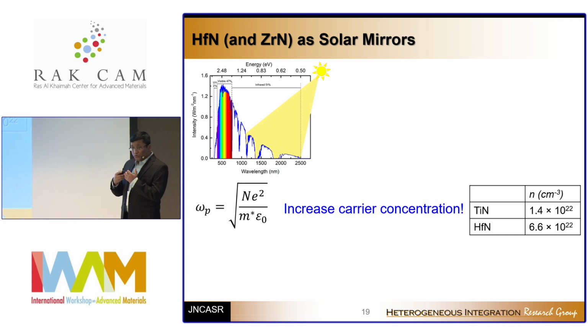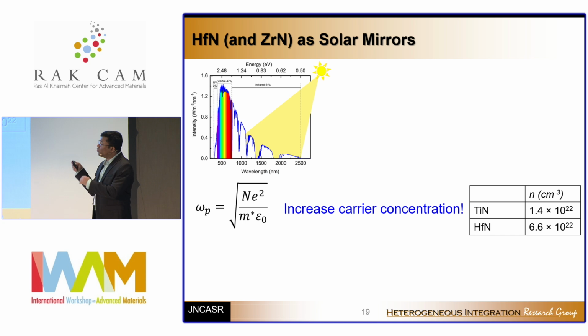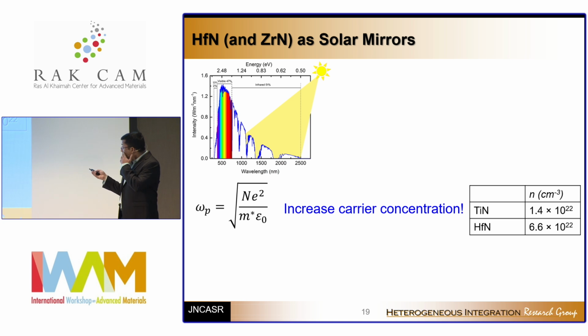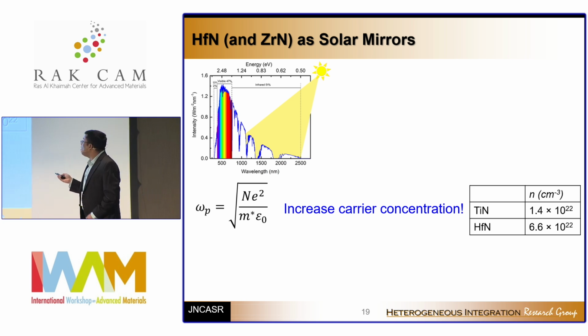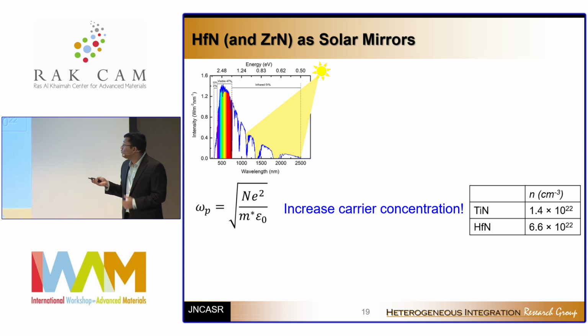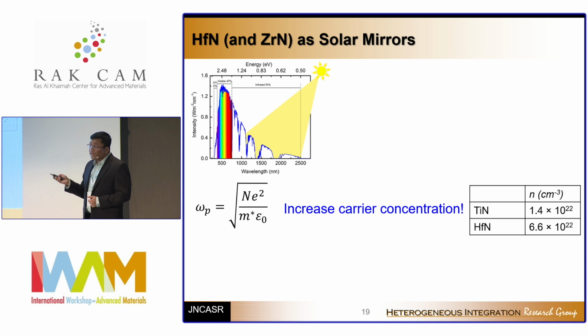So we really had to move to a different system where we can push the ENZ much deeper into the UV spectral range, and the only way you can push the frequency deeper in the UV spectral range is by increasing the carrier concentration. So the choices were not that difficult. You just go below the periodic table from titanium to hafnium nitride to zirconium nitride, and their inherent high carrier concentration basically should be able to give me a mirror that will reflect the entire solar spectrum.